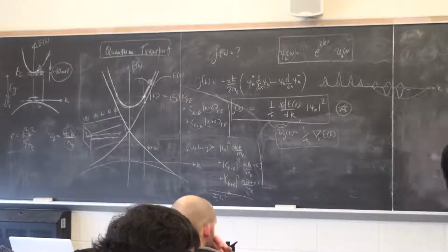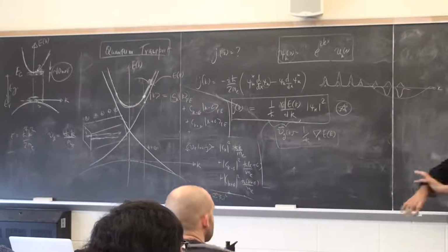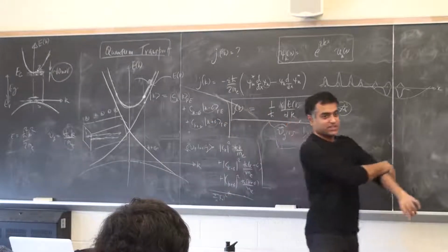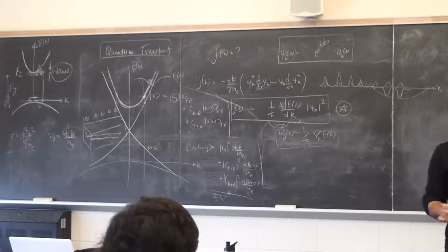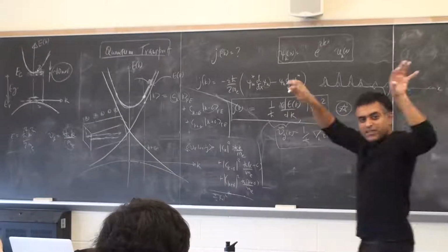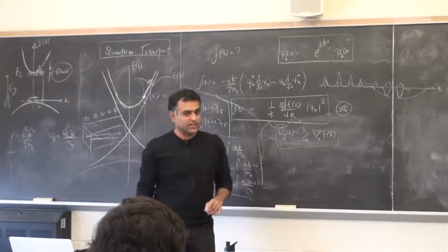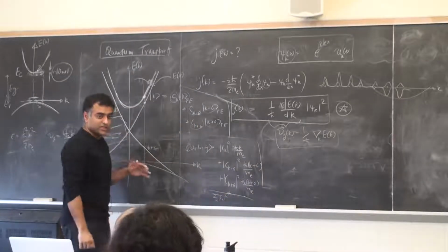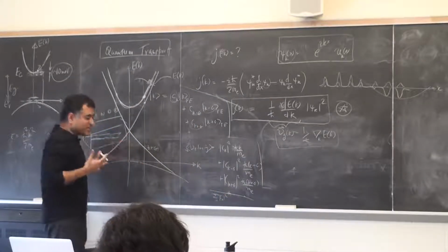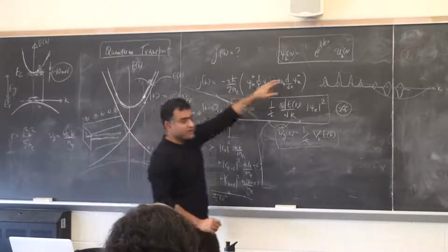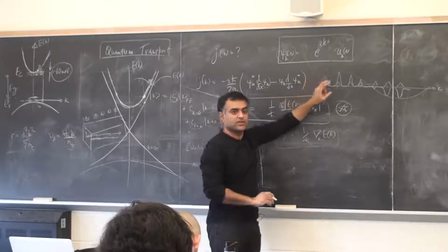Well, what if you're doping periodically? If you dope periodically, it will not scatter. It's a very interesting point. The dopants also form a mini band, so it will not scatter. Anything that is periodic, a potential that's periodic, you have to absorb it in the band structure. It will tweak your Bloch function slightly, change it a little bit, but it will not scatter the electrons.